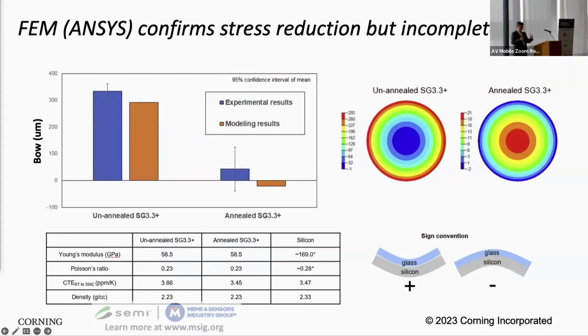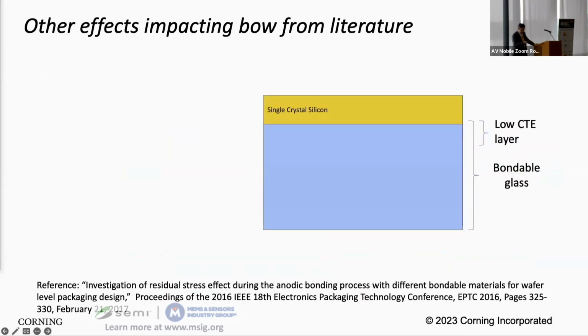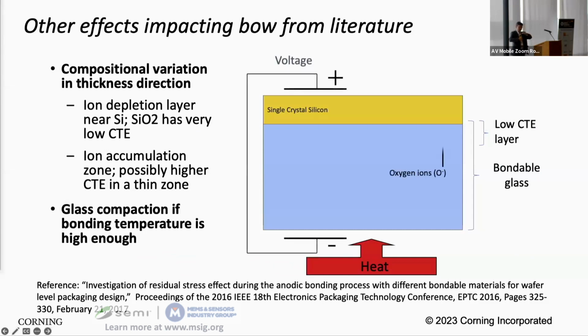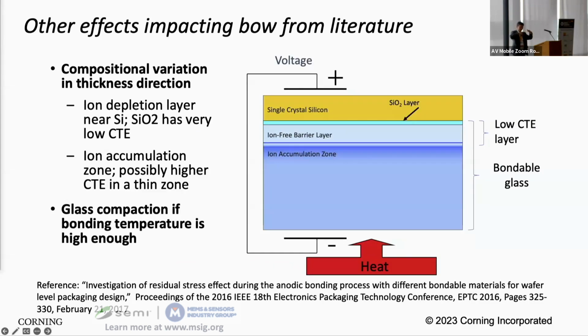And then we did some modeling, and the modeling largely can explain the bow reduction due to CTE match, but we didn't really 100% predict the direction of the bow. And the reason is when you do anodic bonding, I mentioned earlier, there's ion mobility. You actually have a layer of glass where the sodium is totally gone, and the CTE of that portion of the wafer is now essentially 100% silicon dioxide and not the original glass. So there's change in overall CTE due to the anodic bonding process itself, and that made the theoretical match less than perfect.